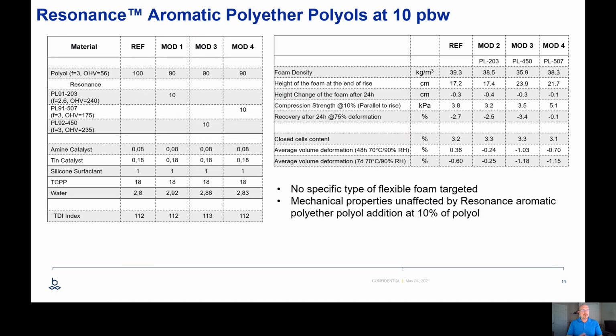Here's one of the formulations where we just put 10% of the polyol as our particular materials, the 203, 507, and 450. You can see the amine catalyst, the catalyst that's used, the silicone surfactant at 1 part. We're using TCPP at 18 parts for this particular formulation. The goal, of course, is to see what happens when we reduce that. But I just wanted to show you the type of foam properties that we get.